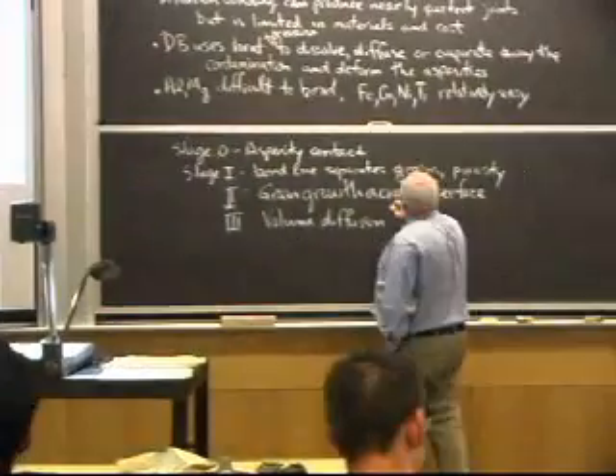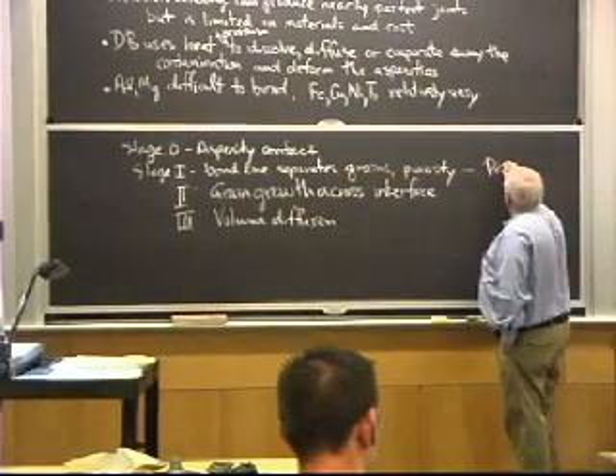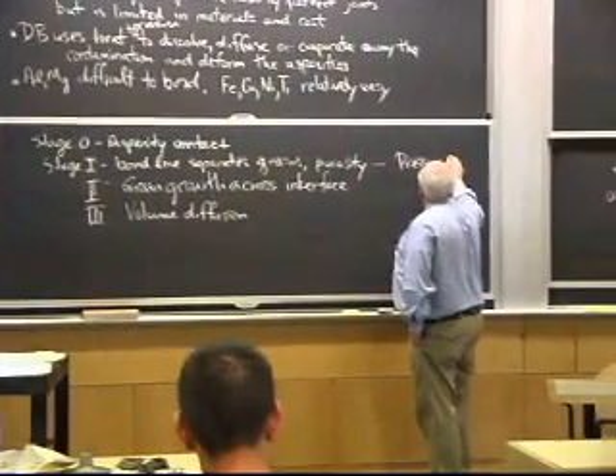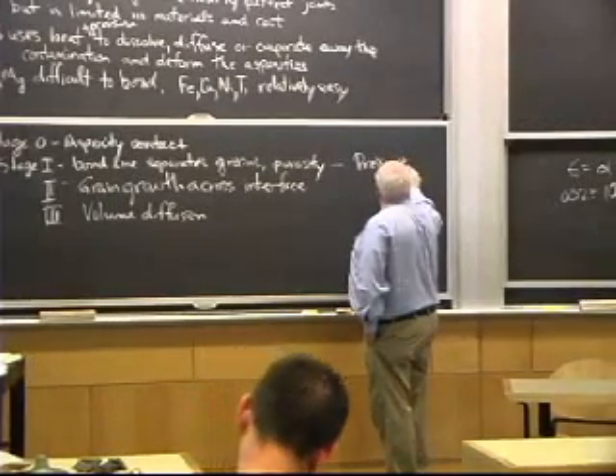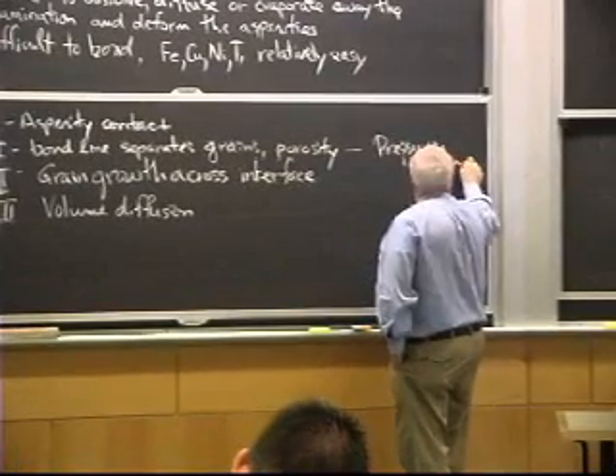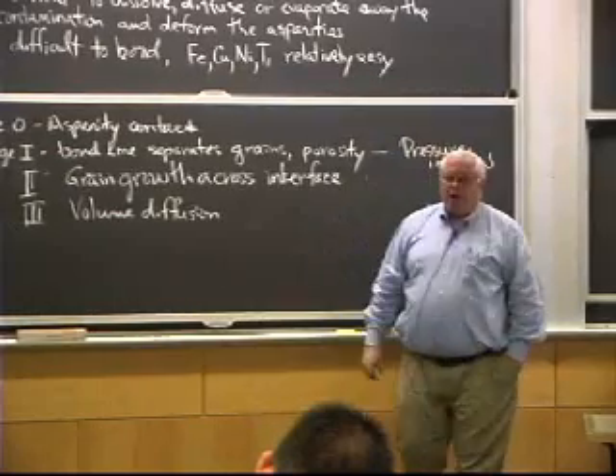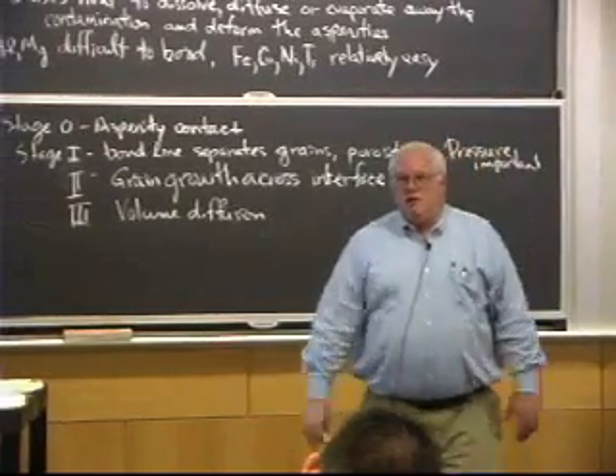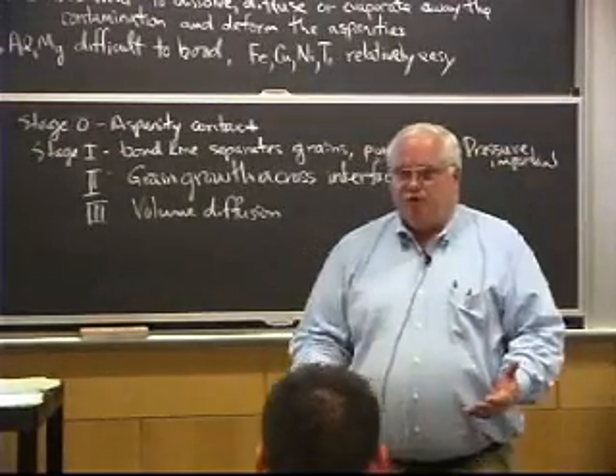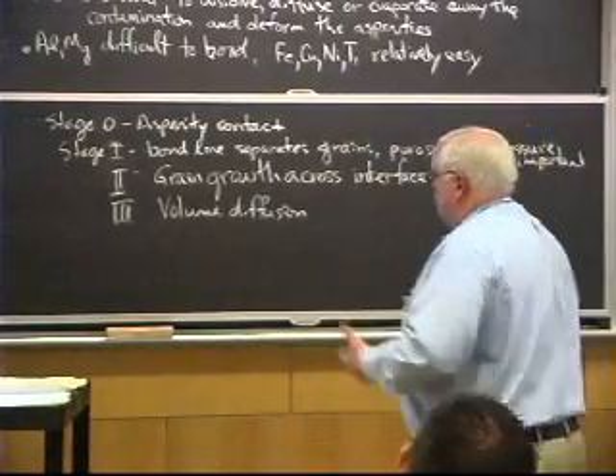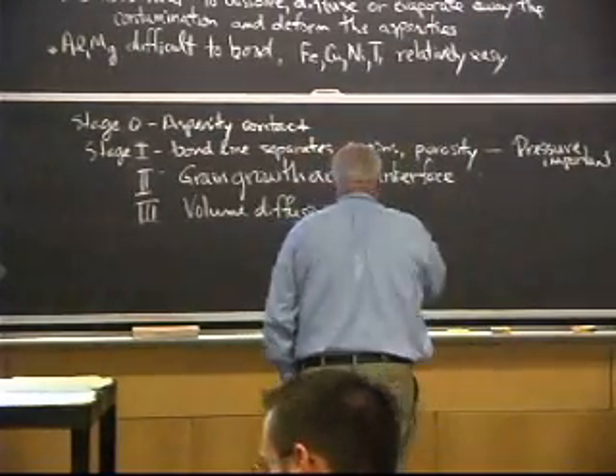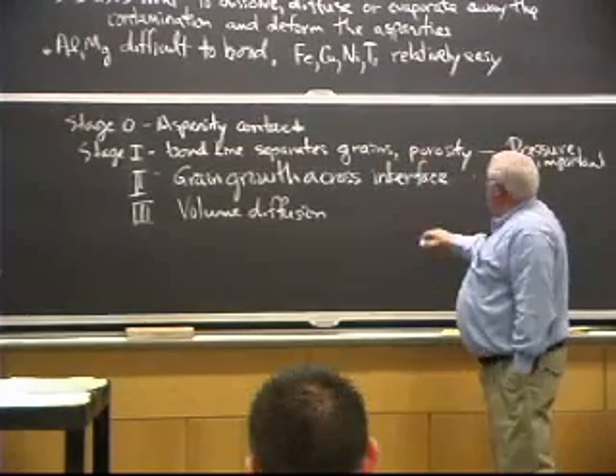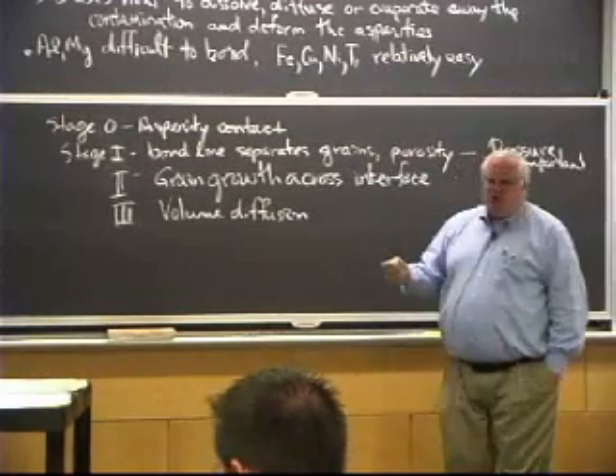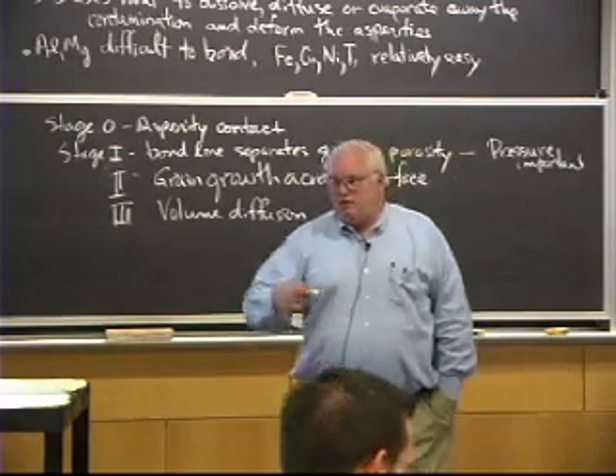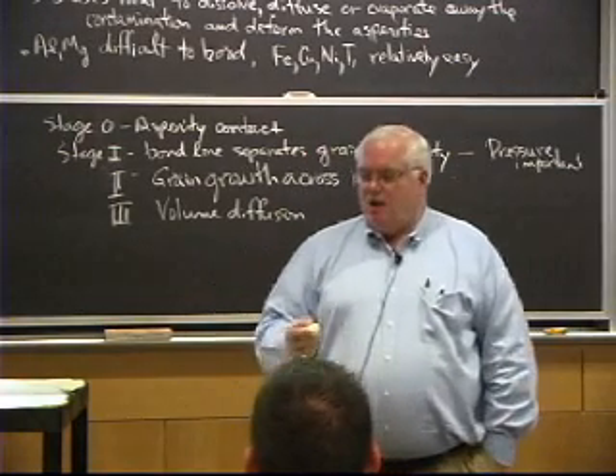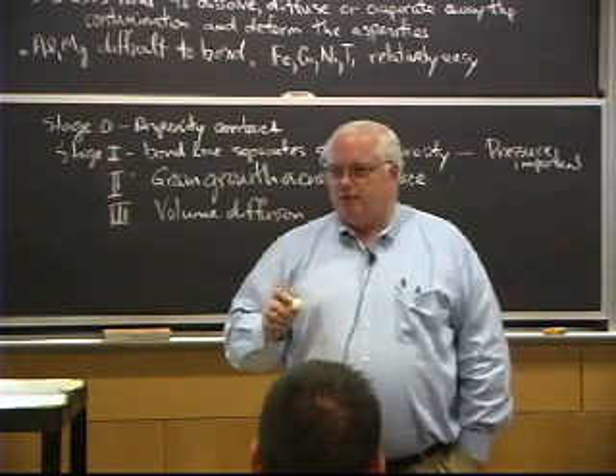So it turns out it's also interesting that at this point, pressure is important. But for these two, you no longer need pressure. The thing is, you've already bonded it together. It just doesn't have a very strong bond. It's got a perforated grain boundary in one case, and it's got porosity within the grains, which is aligned in some sort of plane. But after this, it's really only in the first few hours of a diffusion bond. You may have tens of hours for the diffusion bonding cycle, but it's only the first few hours you need to apply the pressure.